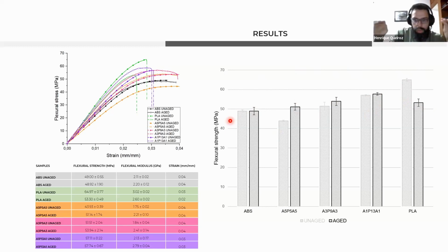And so they reached a point where they stabilized, where the one layer of ABS at the outset, at the outer layers, was damaged by the marine environment, but it reached a point where it basically stabilized, and it remains slightly above the pure PLA.